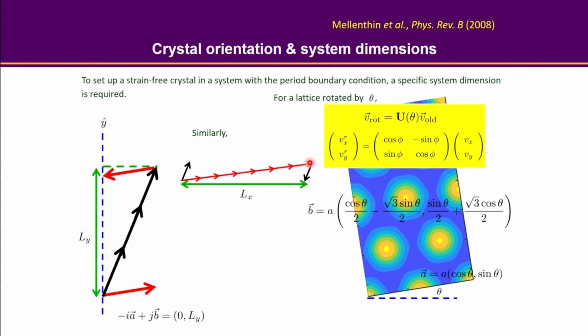and you are going through different atoms, and a new atom can appear here, right? So in the x direction, the system could also be periodic. Just the direct translation from what we explained graphically would be n times of the a factor minus m times of the b factor, that will bring you back to the horizontal axis, which means y equal to 0, right? And whatever we are getting out of this length, that will be my simulation dimension in the x direction. Okay?